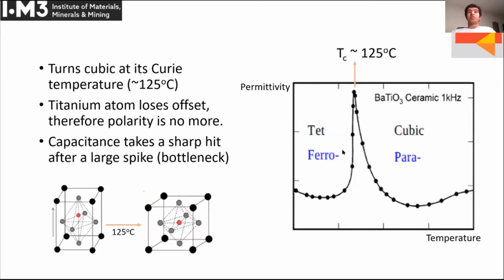It turns cubic at what we call the Curie temperature. The titanium atom can no longer offset, it's just stuck in the center, and that way the permittivity, or the charge storing capability, takes a sharp hit, which is not ideal.